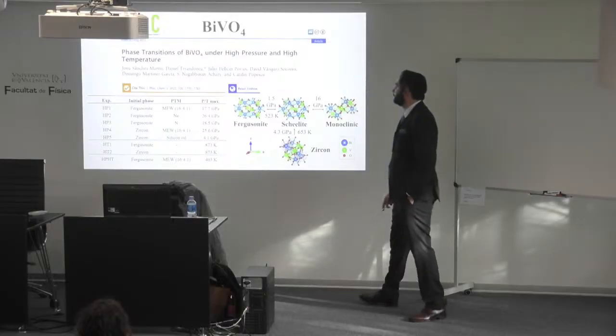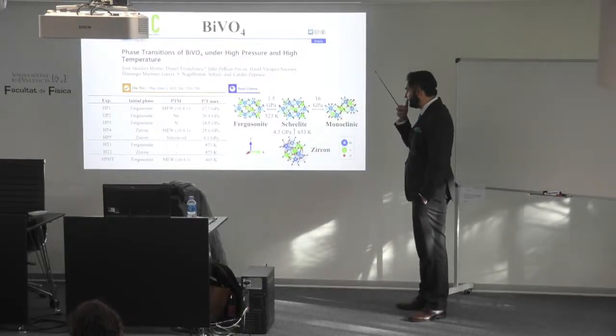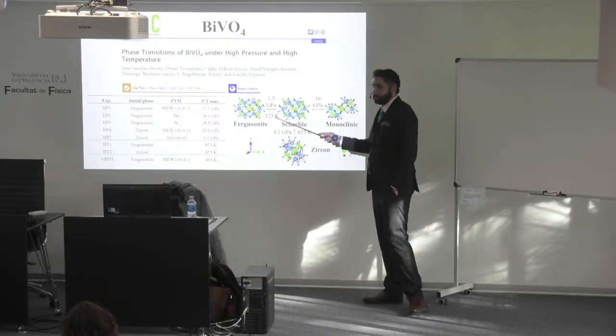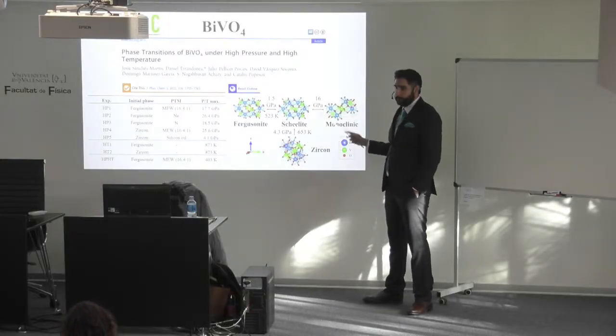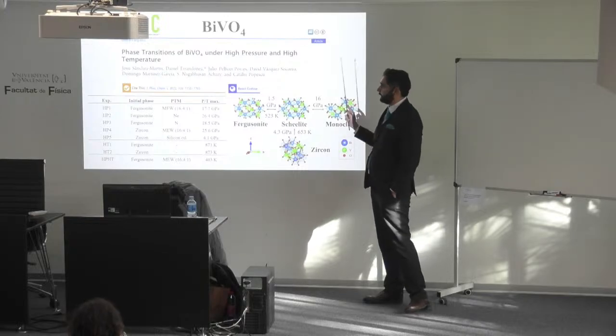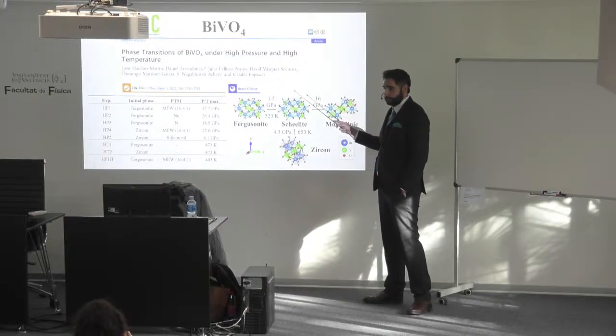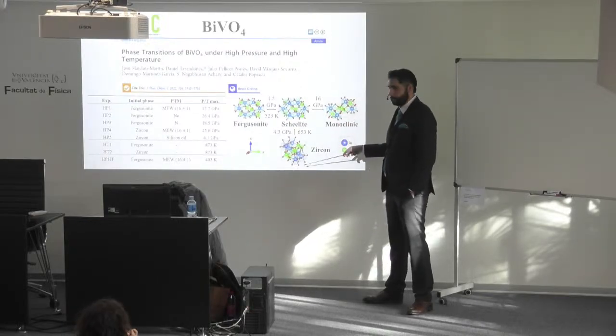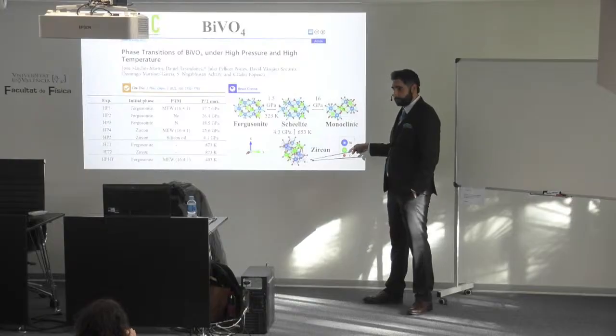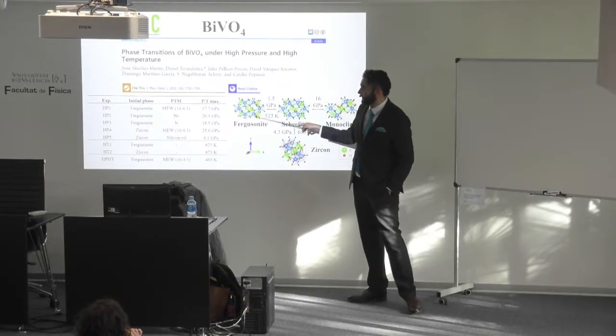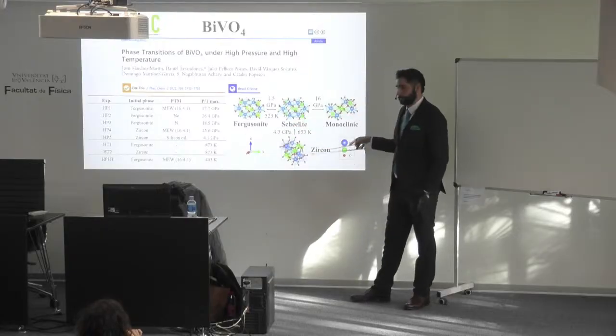So first one, bismuth orthovanadate. This one has a really interesting ferroelastic second order phase transition from fergusonite to scheelite type. If you remember, at the beginning I said that these materials are usually seen in the zircon structure at ambient conditions, but in this case the natural structure is the fergusonite type, and this is metastable.